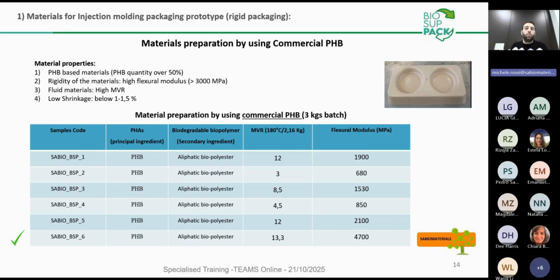In that case, you can see that we have used commercial PHB. The use of commercial PHB was due to the fact that it was difficult, at the end of the project, to receive PHB derived directly from the BSG. So for the first analysis and the selection of the better composition, it was better to start with commercially available PHB, keeping in the formulation the material properties that, as we said before, are a high quantity of PHB, rigidity, high MVR, and also shrinkage, that is another property, very low, between 1 and 1.5, to permit the exact extraction of the final article from the injection molding.